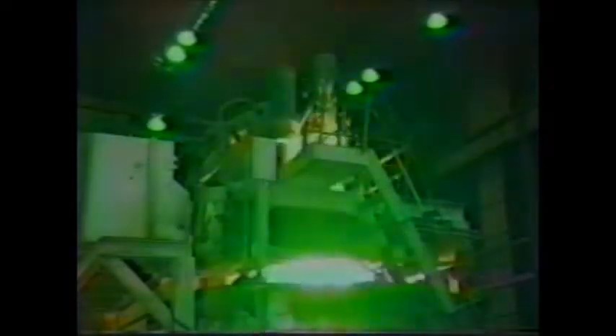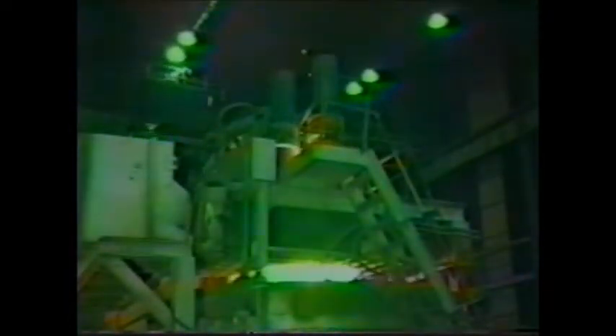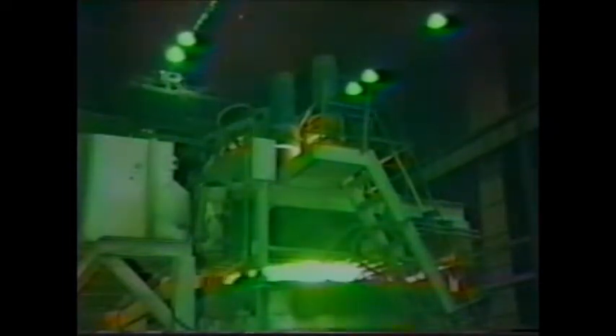The electric arc furnace, the EAF, saves an immense amount of energy by starting with existing scrap steel. This reprocessed steel has a chemistry based on carefully selecting the scrap used in the mix. The carbon and silicon levels are similar to those in BOF steels, but nitrogen and residual element levels are usually higher.